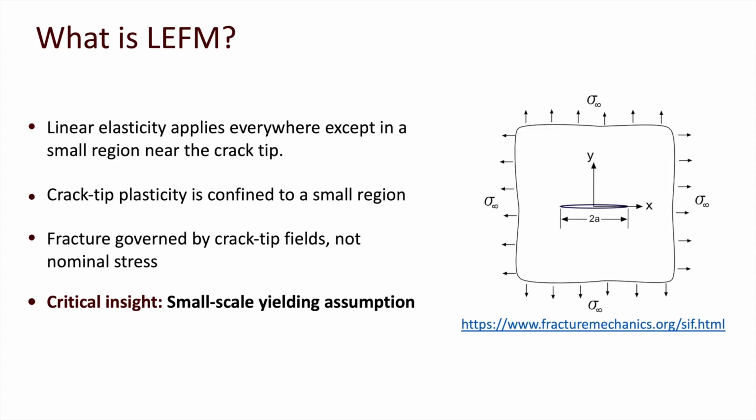Let's begin with the central idea of linear elastic fracture mechanics. LEFM assumes that linear elasticity applies everywhere in the component except in a very small region near the crack tip. Within that small region, some plastic deformation may occur, but it is confined and does not dominate the overall response. Under these conditions, fracture behavior is governed primarily by the crack tip stress field rather than the nominal applied stress. The key concept to remember here is the small-scale yielding assumption. As long as plasticity remains highly localized, LEFM provides accurate and powerful predictions.